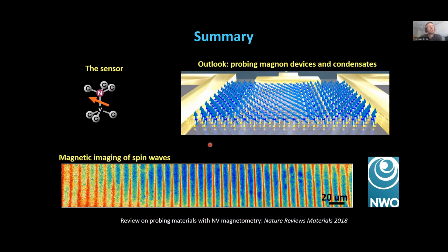That's also right. Yeah. On the other hand, the spectral resolution is very good, right? So the NV center only detects, say, in a 100 megahertz frequency line, and that line you can then tune with an external magnetic field, in principle, all the way up to hundreds of gigahertz. But then you need to apply several Teslas of field. So there's always this question, if you apply a field, how does the system that you want to study respond to the field?